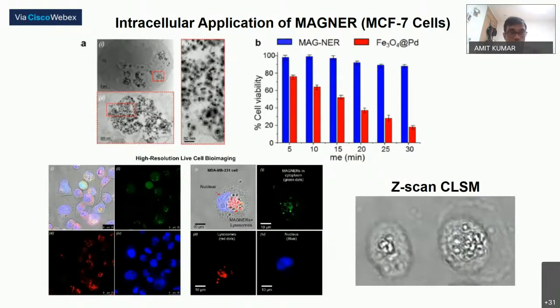Then we fed cancer cells, which is MCF-7, with these nanoreactors and located them with the help of TEM. We could visualize that these nanoreactors are actually located in the intracellular regions, and cell viabilities were tested. And we found that silica-confined nanostructures are much more biofriendly as compared to the naked iron oxide palladium nanocrystals.